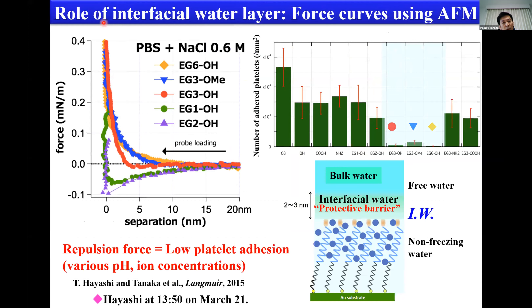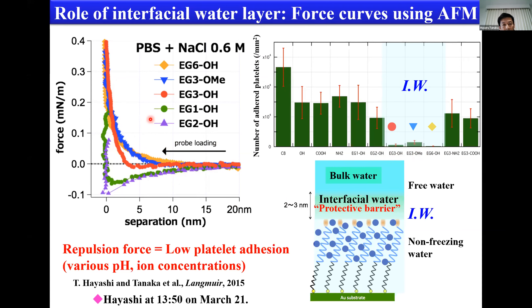This is another example of the role of the interfacial water layer using AFM force curves. Professor Hayashi, one of the invited speakers after my talk, found — in collaboration with Morita-sensei — that surfaces with interfacial water here showed repulsion forces in typical clinical tests using human blood platelet adhesion. Lower platelet adhesion means blood compatibility. Red, blue, and yellow surfaces showed always repulsion force under physiological conditions. Professor Hayashi will explain in detail after my talk.